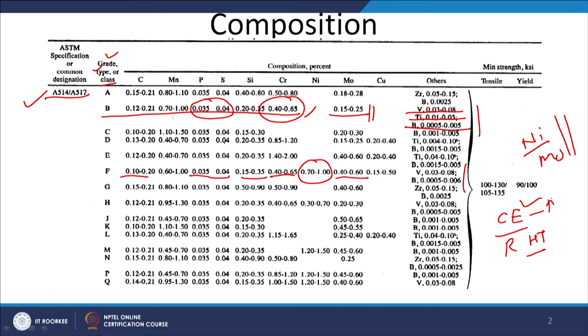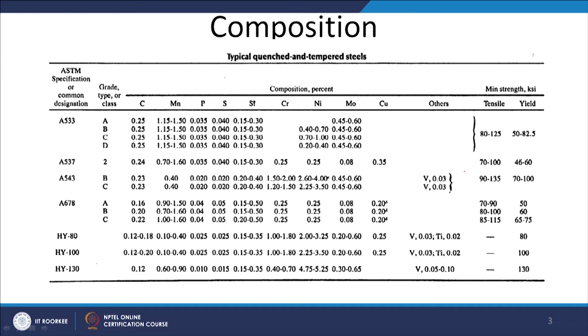So, I mean to say that different elements are present in different types of the 514 and 517 type Q&T steels, and most of these steels are of 100 to 130, or 90 to 100, or 105 to 135. So, in general their strength is around 100 KSI or more. This is yield strength 90 to 100, and the ultimate strength is 100 to 130 or 105 to 135. So, this is one of the most commonly used Q&T steels.